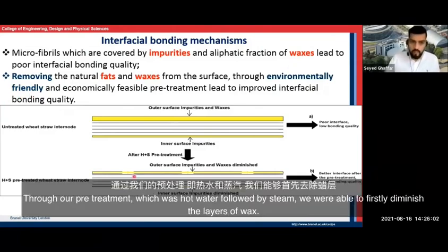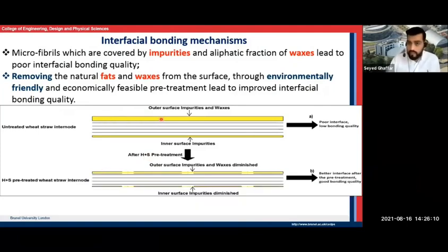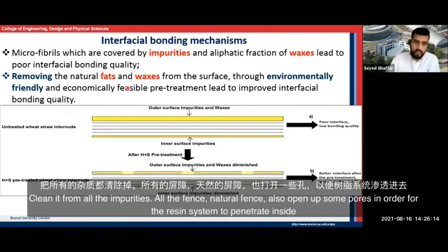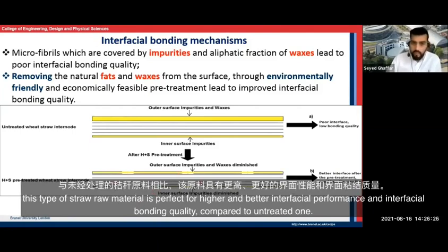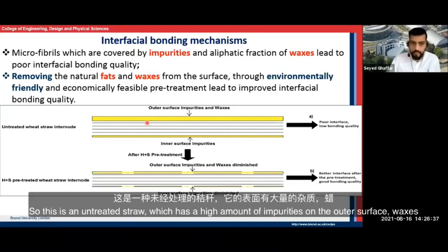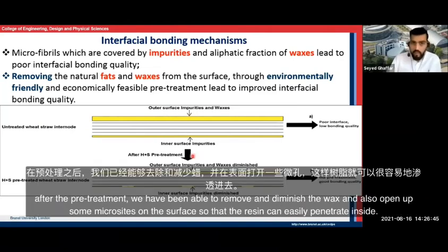So through our pre-treatment, which was hot water followed by steam, we were able to firstly diminish the layers of wax, clean it from all the impurities, all the natural fats, and also open up some pores in order for the resin system to penetrate inside. This type of straw raw material is perfect for higher and better interfacial performance and interfacial bonding quality compared to the untreated one. So this is an untreated straw which has a high amount of impurities and waxes on the outer surface. But after the pre-treatment, we have been able to remove and diminish the wax and also open up some micro sites on the surface so that the resin can easily penetrate inside.